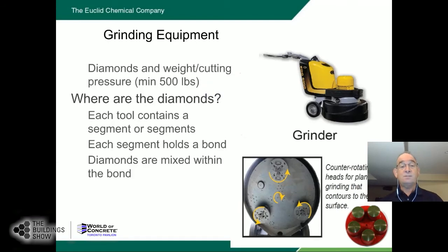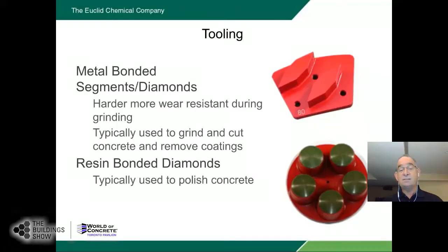Okay, now when it comes to the actual polishing of the material, we use these heavy-duty grinder units. They're weighted to about 500 pounds. There are diamonds in the tools that are used in the polishing process. This has a counter-rotating head with 3 different heads on it, with different diamond grits that would be applied, much like sandpaper, from coarse to fine.